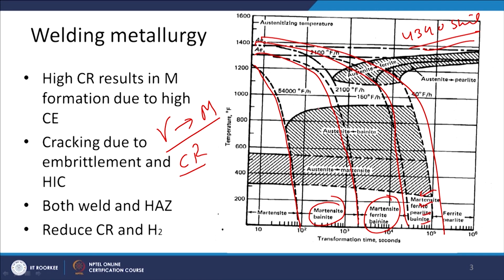So, higher the preheat temperature, lower will be the cooling rate, and accordingly the softer phases will be formed. If the cooling rates are high, only martensite, otherwise martensite plus bainite, martensite, ferrite, bainite, martensite, ferrite, perlite, bainite, and too low cooling rates will be leading to ferrite and perlite only. So, these phases will be determining the hardness, and the temperature at which these transformations are taking place will be determining the possibility for escaping of the hydrogen and reducing the residual stresses. Higher the transformation temperature, lower will be the residual stresses that will be induced.